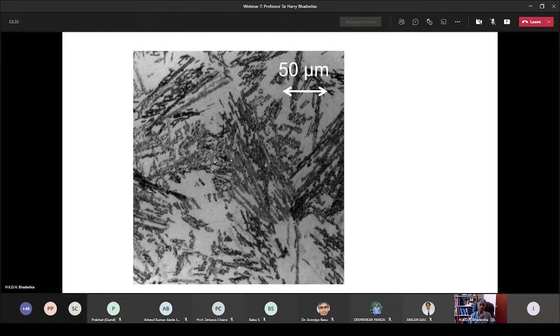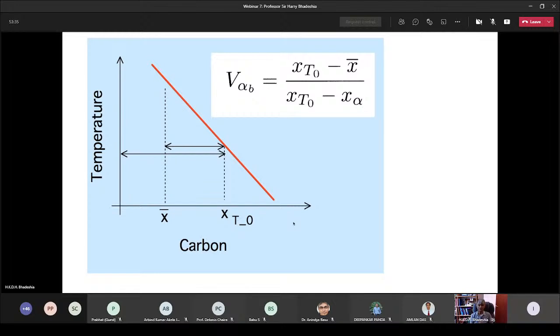So let's see whether our theory tells us something else to try. Going back to our T0 curve here, our goal is to increase the volume fraction of bainite so that the islands of austenite become smaller and smaller. So this is the volume fraction of bainite. This is the T0 curve, and the ferrite carbon concentration will be very small. This is the average concentration in our alloy,